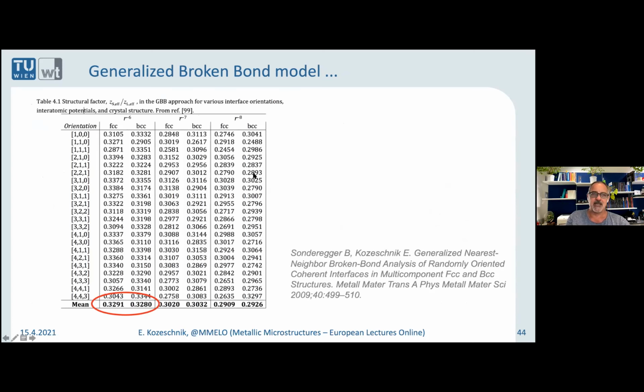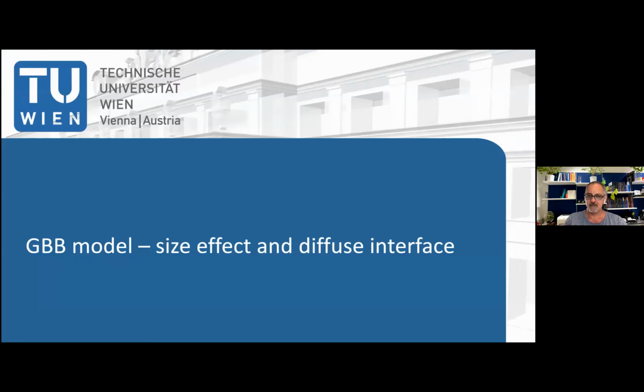And when you look at the table where we made some orientation dependent calculations and then formed a mean value, we could find very close together numbers for FCC and BCC. And this is actually the value for the structural factor that we are using now in all the computations that we do. So the planar sharp interface model in the generalized broken bond approach does give you reasonable predictions now with good accuracy, also for BCC and for FCC.